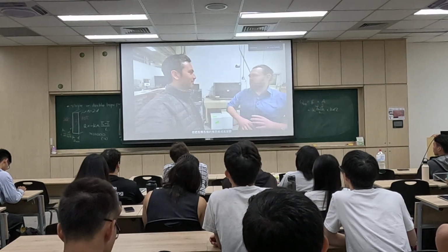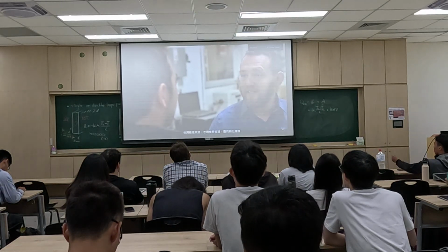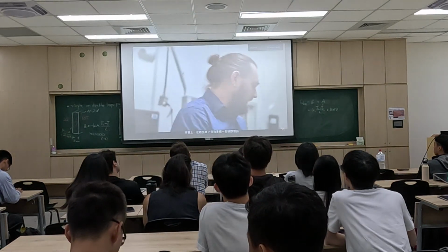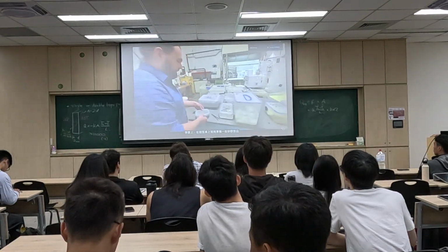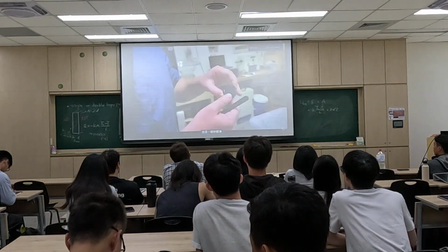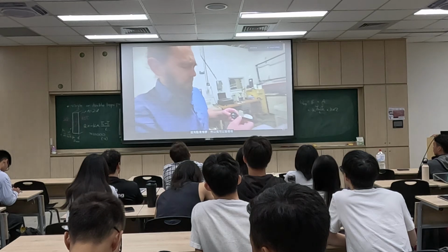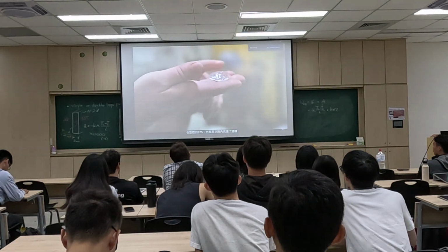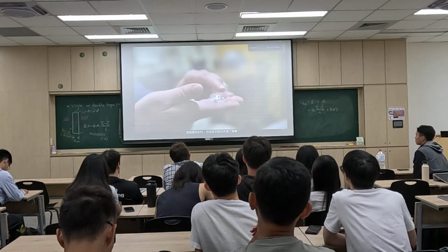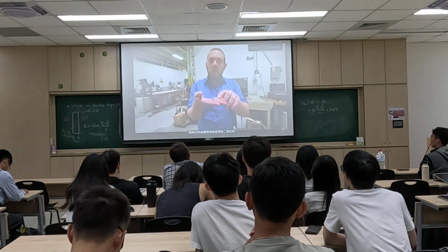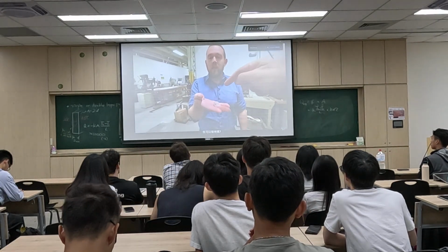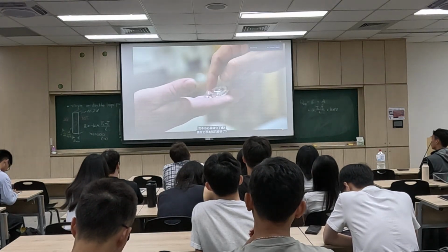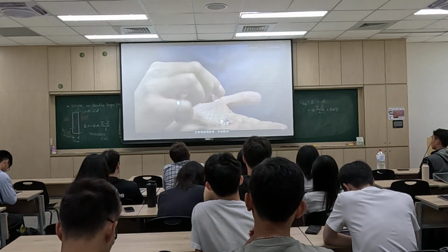He made aerogels out of all sorts of things. He made them out of eggs, out of rubber, out of nitrocellulose, and included there is silica. Actually, right here on the table, I have some examples of silica gels. This is a wet silica gel. It's kind of rubbery, so I can just carve out a piece. It is 97% alcohol inside its pores, and then the remaining 3% solid is amorphous silica. It's kind of rubbery, not that strong.